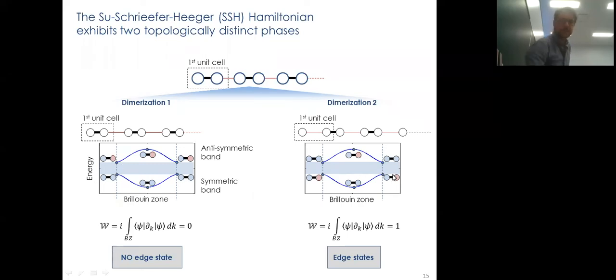But in the other case, because the unit cell is not defined with a dimer, we have the opposite. At the center of the Brillouin zone, yes, the unit cell atoms are still moving in phase, but as we move across and we reach the edges of the Brillouin zone, now the atoms are evolving out of phase. And it is the opposite when we go to the upper band, where at the center of the Brillouin zone, we have asymmetric wave functions within the unit cell, and at the edges, we have symmetric ones. So you see again, we have this winding of the symmetry properties that I was describing earlier, and we can relate this to the topological invariant.